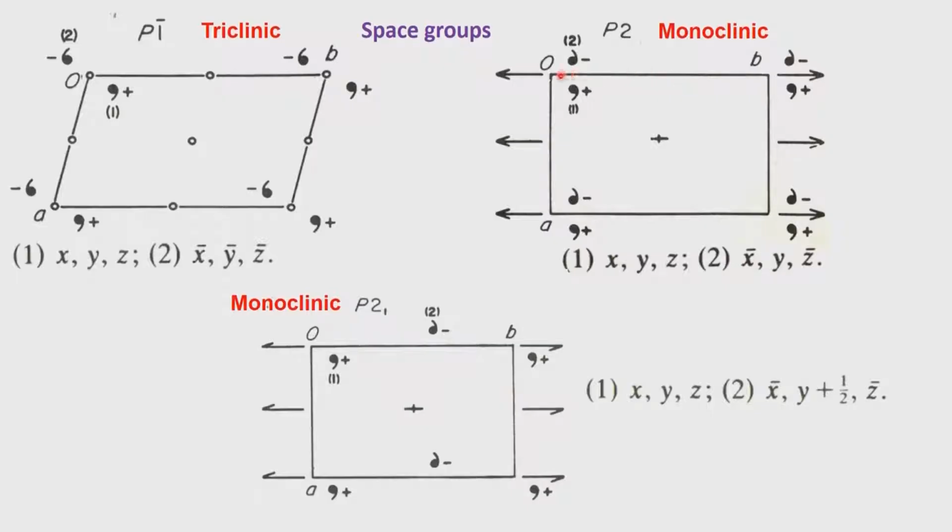And then we also have the possibility of the same special position coming at the repeat distance along the A direction. Other than that, we have only the general positions x y z and x bar y z bar, and this generates 2 equivalent points. The equivalent points on one translation take the objects outside of the unit cell, and therefore Z is always 2 in P2.